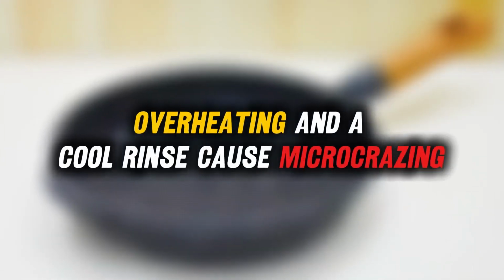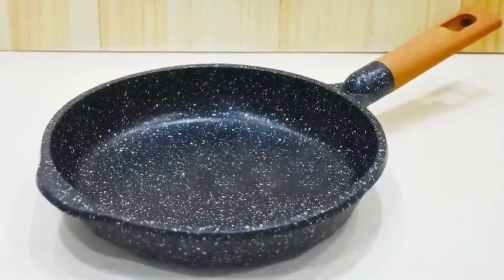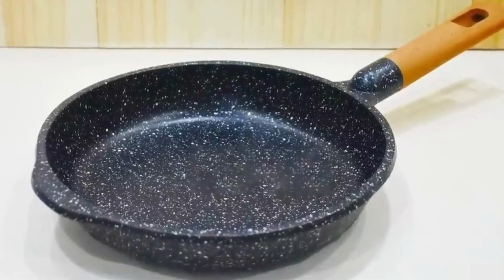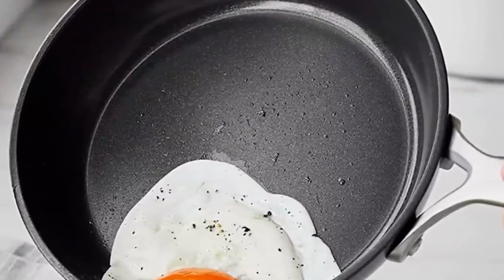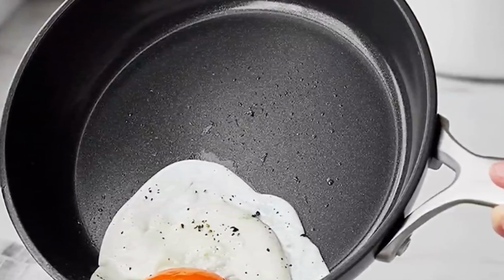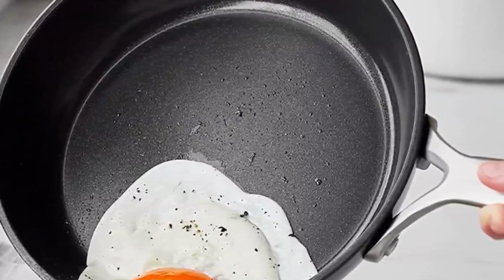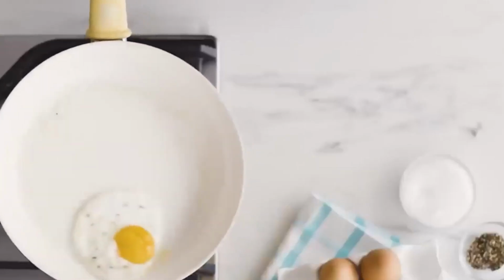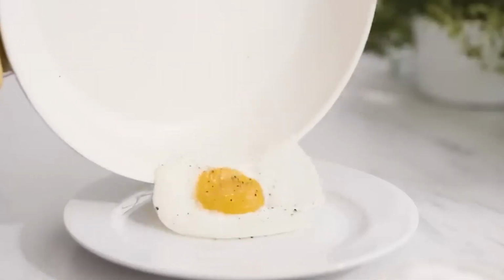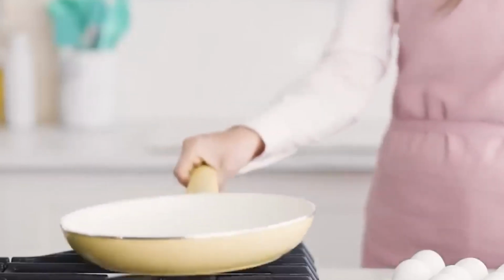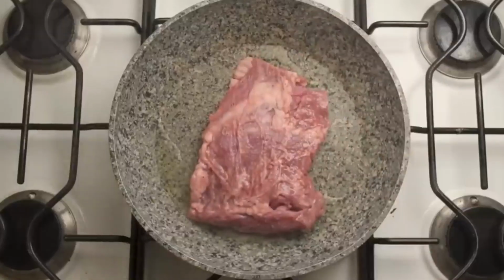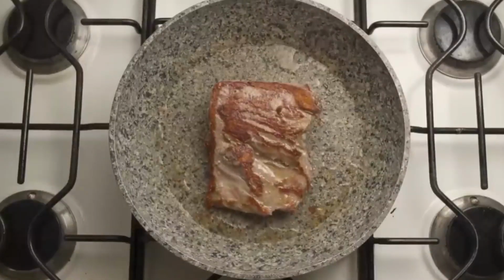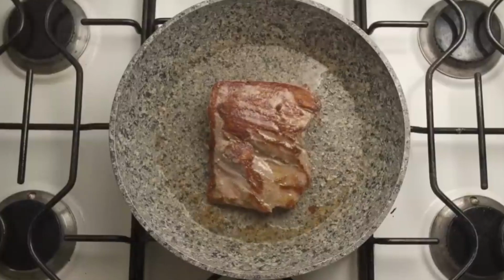Overheating and a cool rinse cause micro-crazing like a dry lake bed. Food grips, you crank the flame, and the glaze breaks down faster. Some budget lines have uneven layers, so high spots gray and rough first. Abrasive pads strip the slick top, and tests show non-stick drops quickly with scouring and high heat. Reputable makers screen for heavy metals and publish certifications. The lowest cost sets often don't.